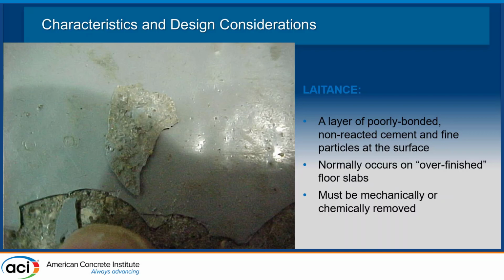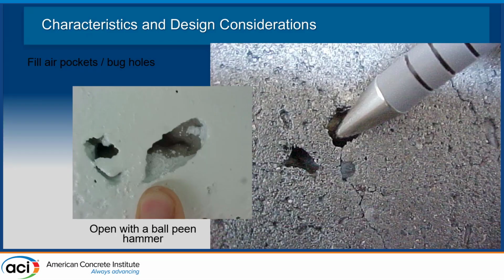So that has to be removed, whether it's by grinding, blasting, water jetting, or even a chemical removal like acid etching, depending on the situation and what is practical on that project. So then we also want to talk about bug holes. And bug holes are just like air bubbles that don't quite make it to the surface.